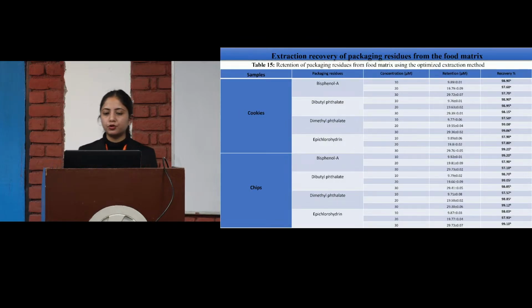Then the extraction recovery of the packaging residue from the food matrix. This is the concentration which we spiked into the food sample. As we spiked 10 micromolar, 20 micromolar and 30 micromolar of the bisphenol in the cookie sample, the recovery percentage is 98%, 97% and 97.70%. Then in the cookies, we added the dimethyl phthalate and the epichlorohydrin into the cookie sample with the same concentrations of 10, 20 and 30 micromolar.